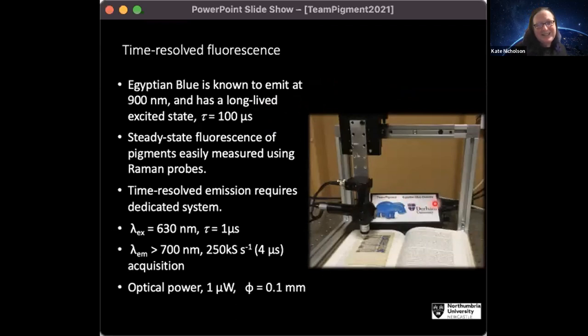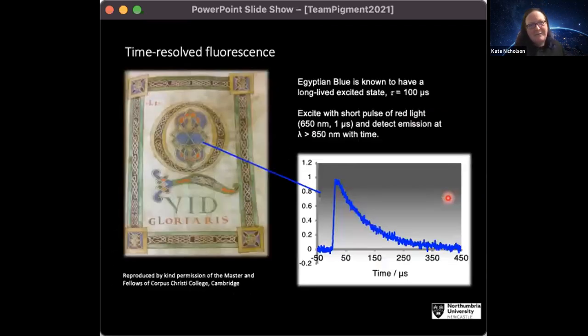This is dedicated just for measuring the fluorescence lifetime of Egyptian blue. It's a time-resolved measurement, so you illuminate with a pulse of light and measure the emission of photons after that. It also had to be low power. So we're making sure we're staying within our power limits again. And then we went and looked at the book that contained Egyptian blue.